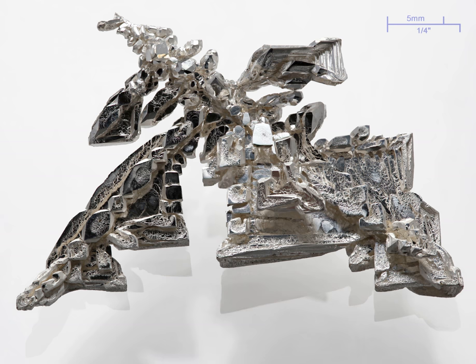So the primary production of silver requires the smelting and then cupellation of argentiferous lead ores, a historically important process. Lead melts at 327 degrees Celsius, lead oxide at 888 degrees Celsius, and silver melts at 960 degrees Celsius. To separate the silver, the alloy is melted again at the high temperature of 960 degrees Celsius to 1000 degrees Celsius in an oxidizing environment. The lead oxidizes to lead monoxide, then known as litharge, which captures the oxygen from the other metals present. The liquid lead oxide is removed or absorbed by capillary action into the hearth linings.